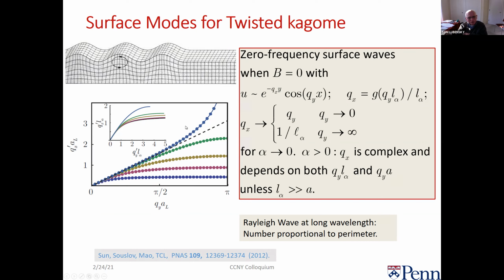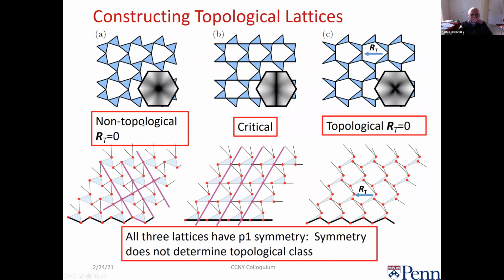It depends upon q_y. And as we go down to q_y equals zero, all of the different modes for different values of the twist angle asymptote to the continuum calculation, which you can find in Landau and Lifshitz, for example. So we now see that we have a set of zero modes which obey the counting rules, which are associated with the